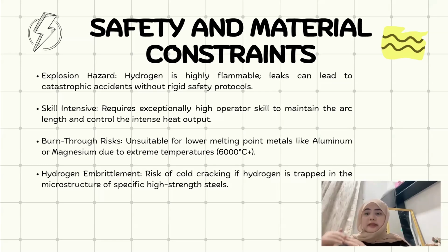Third, a burn-through risk. Because the extreme temperatures generated by the recombining hydrogen atoms can exceed 6,000 Celsius, AHW is completely unsuitable for lower melting point metals like aluminum or magnesium. Attempting to weld these thin or low temperature materials results in instant burn-through.